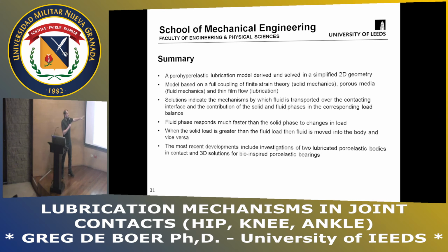And this has indicated some of the mechanisms by which fluid is transported over the contacting interface, and in particular, whether the solid or the fluid phase is carrying the load. The fluid responds much faster than the solid, and when the solid is greater than the fluid in terms of the load, flow is moving one way or the other. Okay? So some of the more recent developments include these 3D solutions and bio-inspired type bearings.